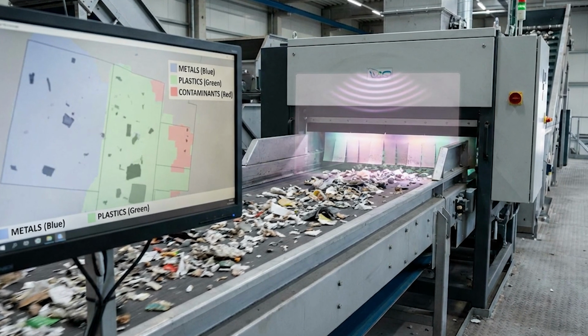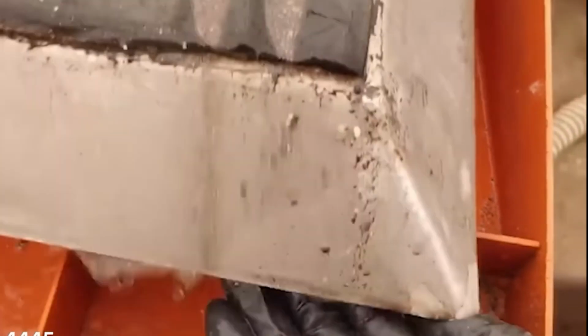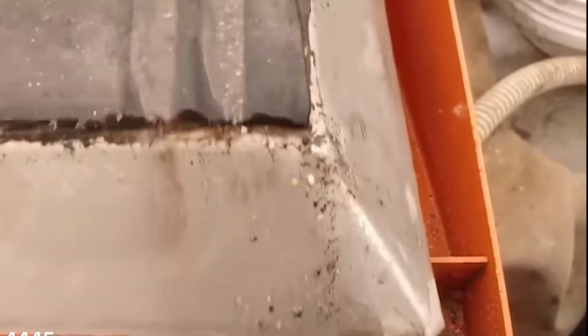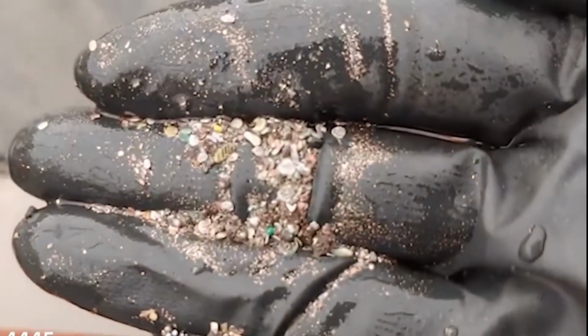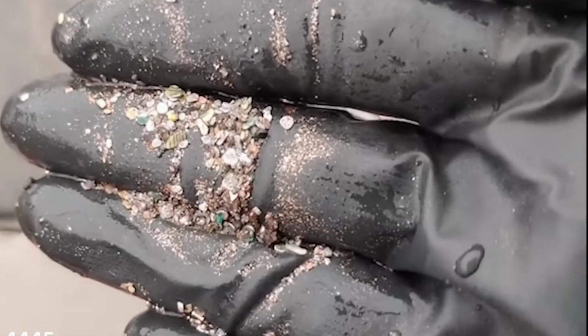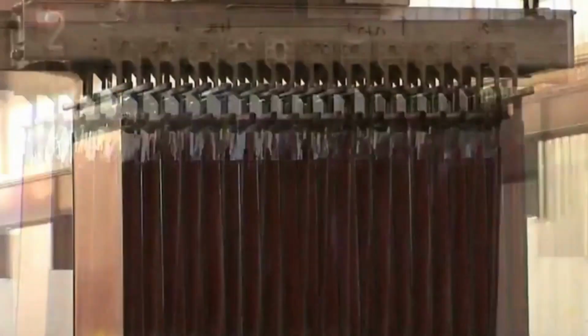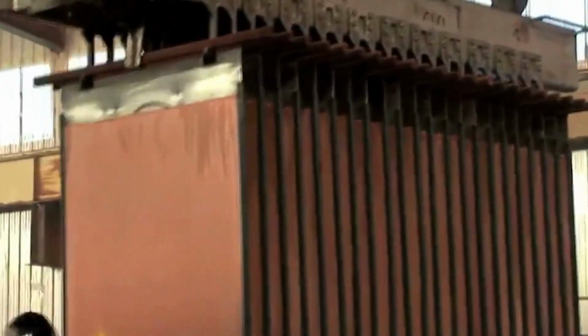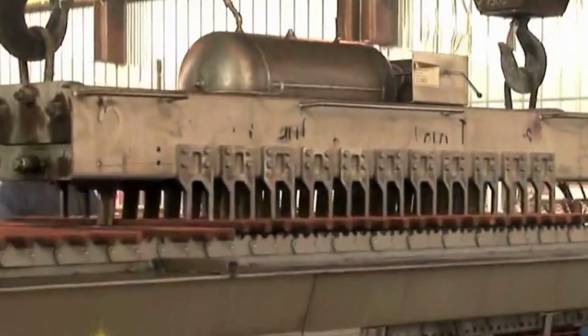5. Electro-recovery and electro-refining. Now value becomes visible. Once metals are dissolved, you pull them back out with electricity. For copper, this is the workhorse moment, electro-recovery. This is the moment value becomes visible. A sheet of copper grows, atom by atom. And 1 setting decides whether it plates clean or burns on the surface. Current density, tuned so copper deposits smoothly, instead of turning rough and brittle. If pH or impurities drift, cathodes plate garbage instead of copper.